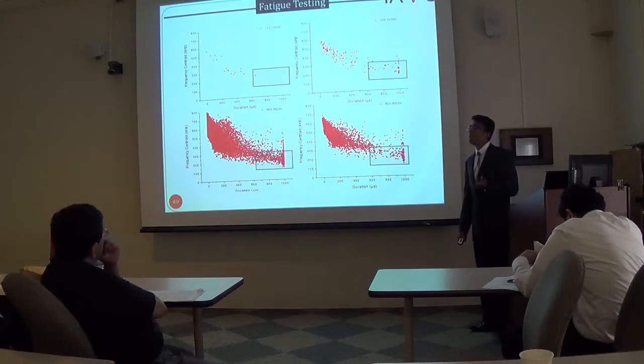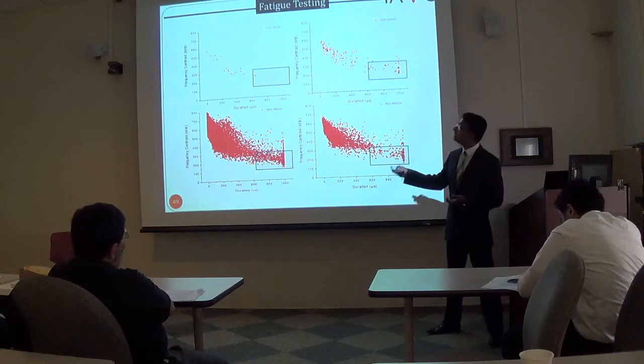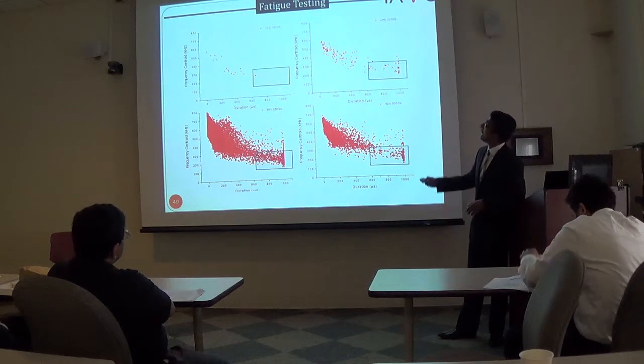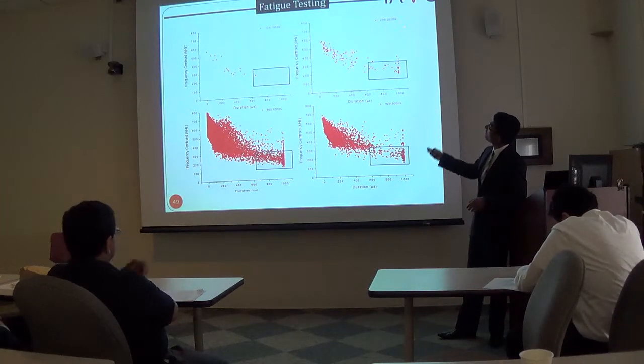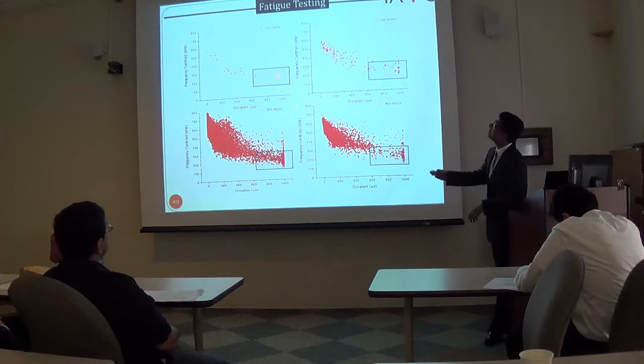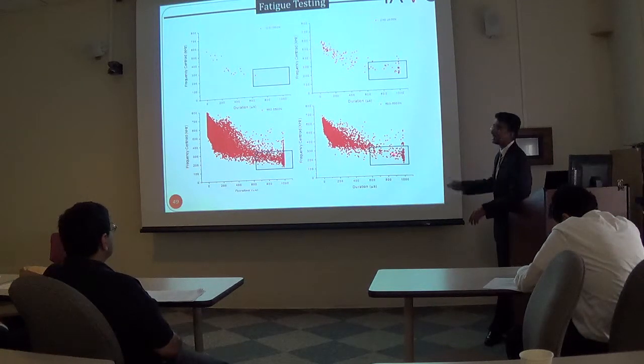frequency contents. So in order to develop an AE feature analysis that was sensitive to the extent of debonding, novel advanced frequency analysis such as the frequency centroid was correlated with duration and was plotted as a function of the different applied fatigue loading limits, as you can see here. It can be seen that as loading increased, signals associated with the low frequency centroid and a high duration were seen to increase with the subsequent loading in the material.